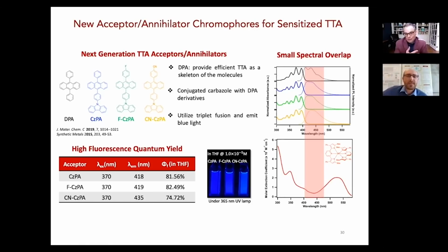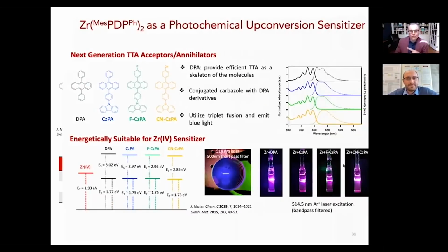And the key thing really, in terms of zirconium, was we figured let's at least do one thing different. Can we get to this maximum 40% efficiency? That was really what drove us. And the surprise was the combination of the fact that the zirconium has no deleterious side reactions. So it doesn't annihilate. We actually did this experiment. This is what's crazy, Christoph, this is what is shocking when you really think about it,